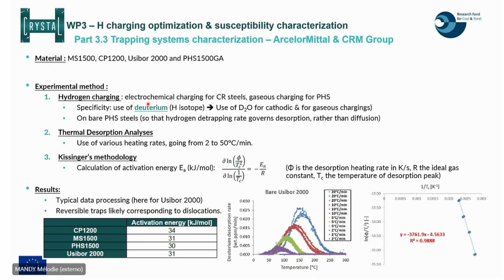Specificity here is the fact that we used deuterium for this study at ArcelorMittal and at CRM. Deuterium is the hydrogen isotope with one more neutron. It is very interesting because it's far more scarce than hydrogen. So we are sure that we can perfectly identify it when we find it in the results.